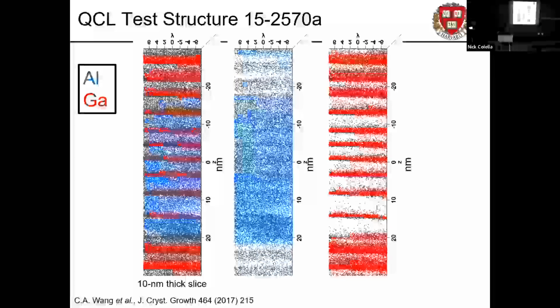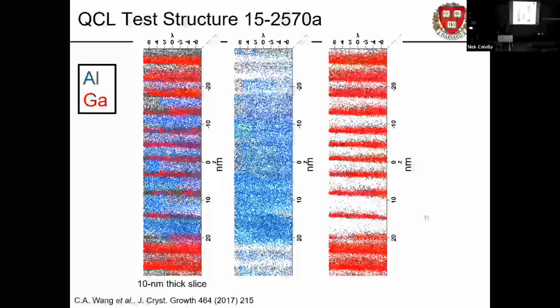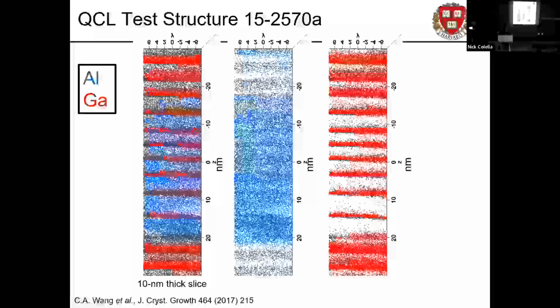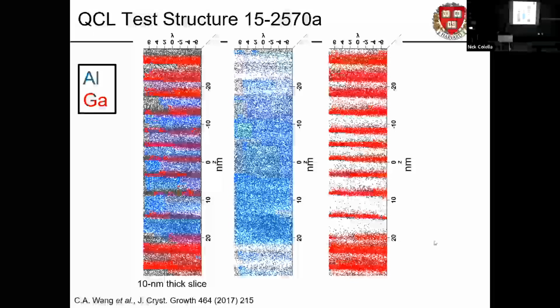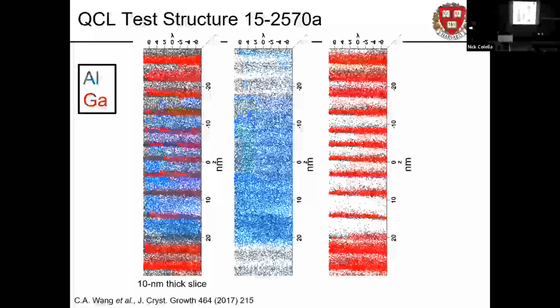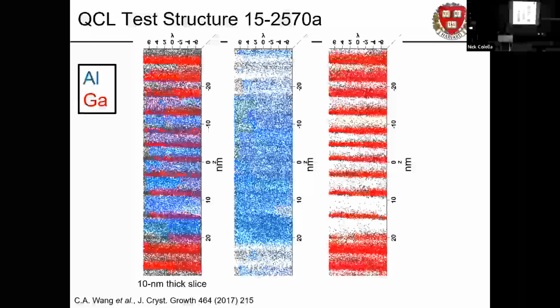We got red atoms trailing upward from each one of these red stripes. Now these are gallium atoms. This is indium aluminum gallium arsenide. And the idea is they started at the bottom of this stack and they grew upward, and they turned on and off the little nozzles that squirt one atom or another. At least they tried to, but it turns out the gallium nozzle got stuck open, and it kept on flowing gallium longer than it should.